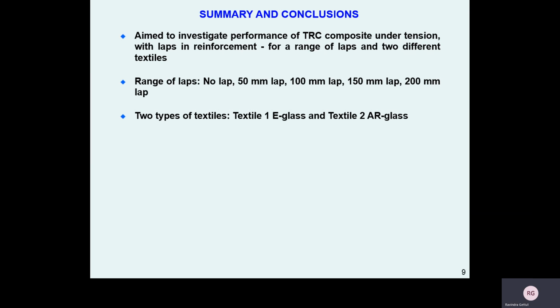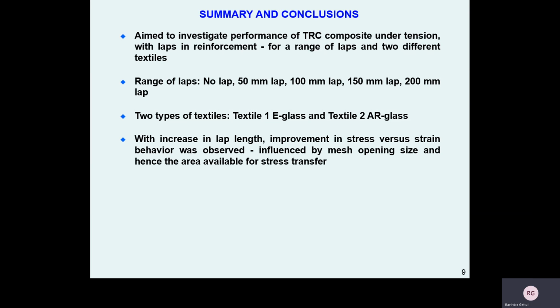It was observed that there is a certain drop in strength up to a particular lap length in comparison to a monolithic case without lap. For the chosen textiles, considerable performance was observed for a minimum lap length of 150 millimeters. However, it has to be noted that this was highly influenced not only by the size of mesh opening but also by the area of yarn available at each joint to transfer the stress.